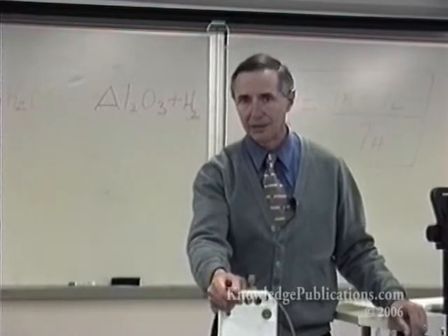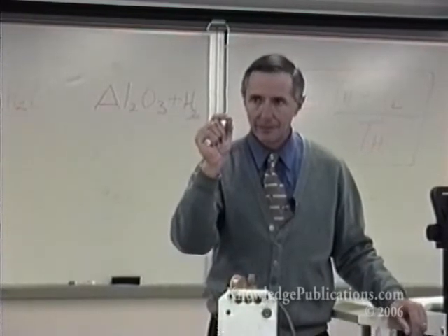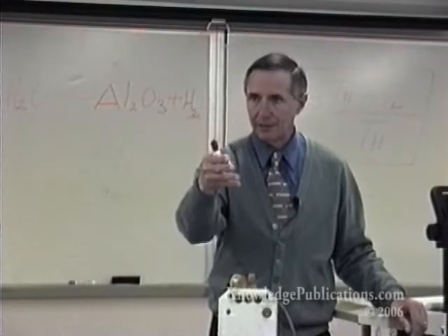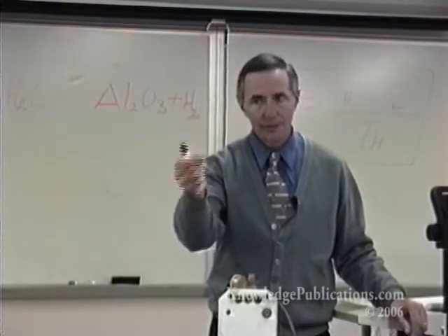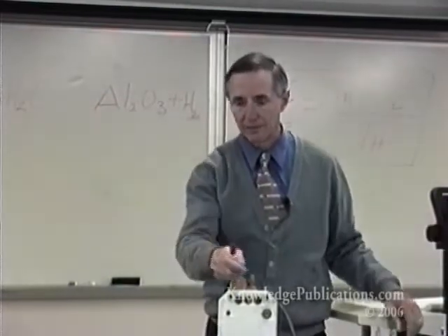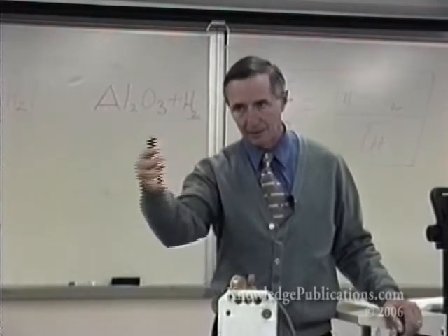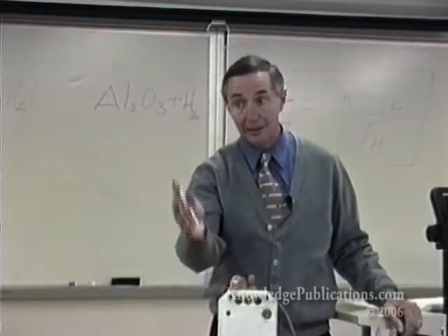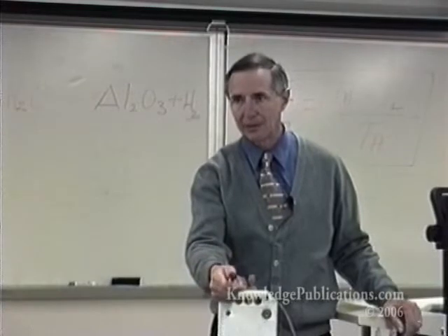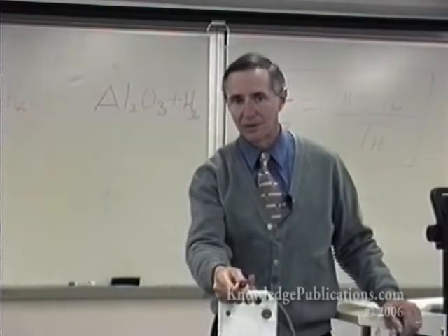If the hydrogen's bubbling, it starts as an ion, becomes an atom, both of which are point blank exposed to the metal, before it becomes diatomic hydrogen, before it gets to be bigger by joining more atoms of hydrogen. It's always going to be available to enter the lattice as an ion or as atomic hydrogen. In that condition, you can embrittle almost anything.